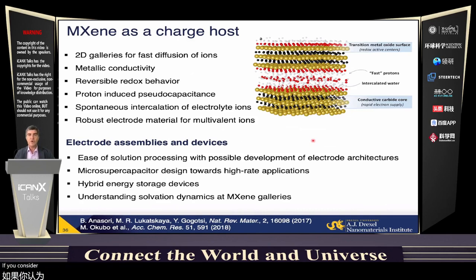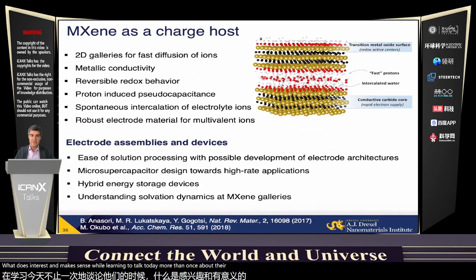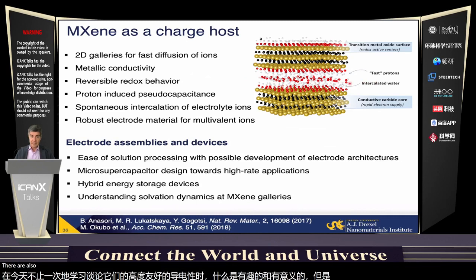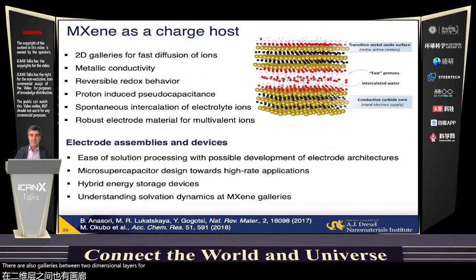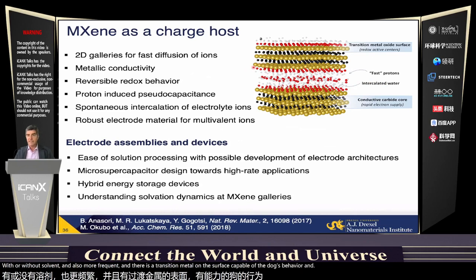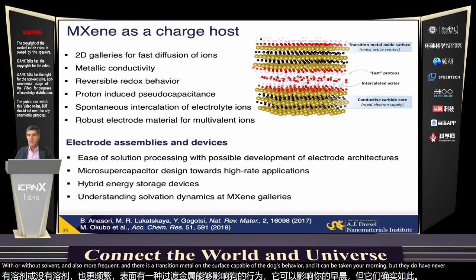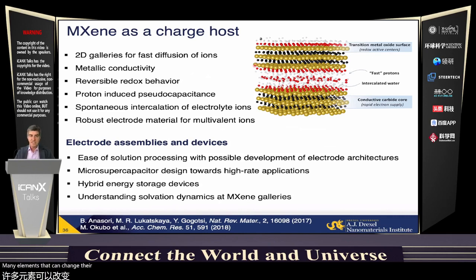If you consider oxide materials used today, those are fairly poor electronic conductors. So if you run a high current through a resistor, you just heat it up, leading to catastrophic consequences. What is interesting in MXenes, we already talked today more than once about their high electronic conductivity, but there are also galleries between two-dimensional layers where ions with or without solvent can also move quickly. And there is a transition metal on the surface capable of redox behavior. And it can be titanium, moly, vanadium, niobium, many elements that can change their oxidation state significantly here.